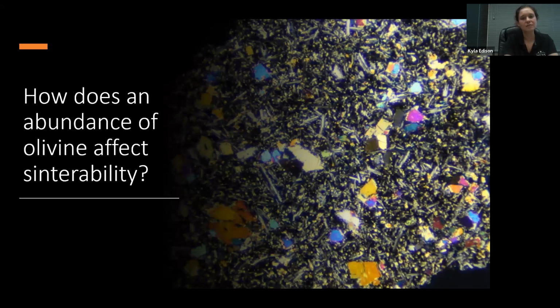And so in this photo that you see is a thin section of Quarry 4. And you can see all the colorful, really nice crystals there. Those are all olivine. And so basically what we did was we subjected all of our materials to X-ray diffraction to get a better idea of exactly what the crystallography, the mineralogy of this stuff was.